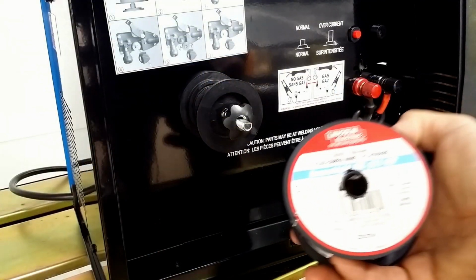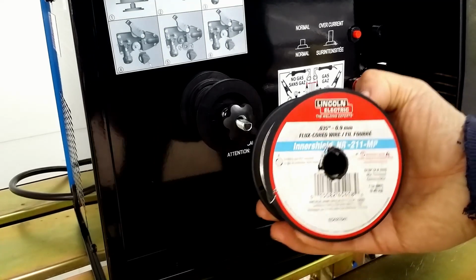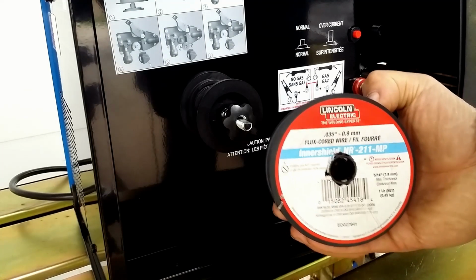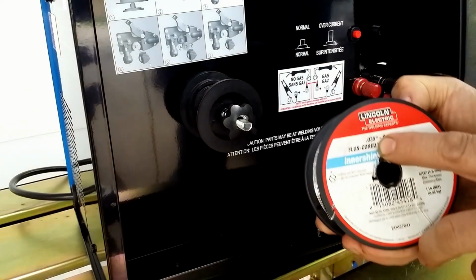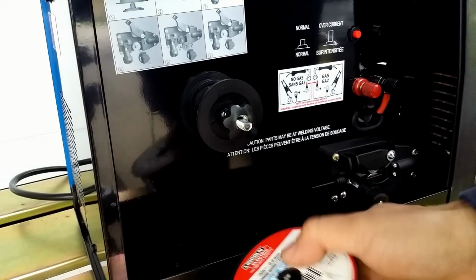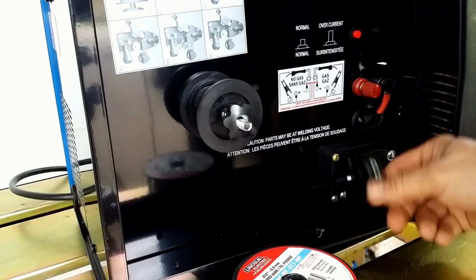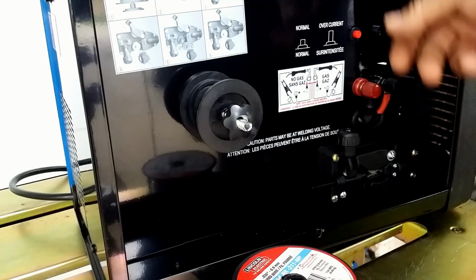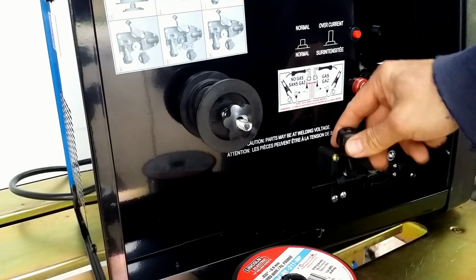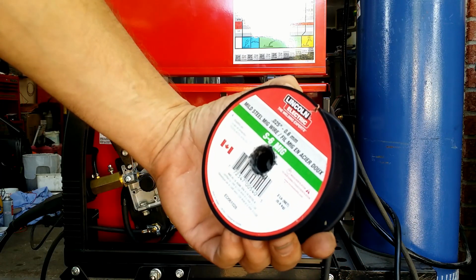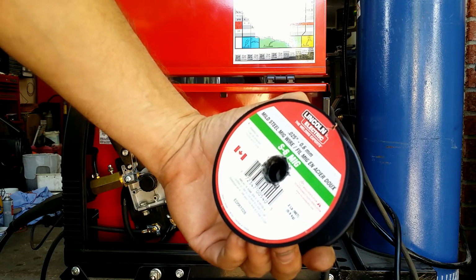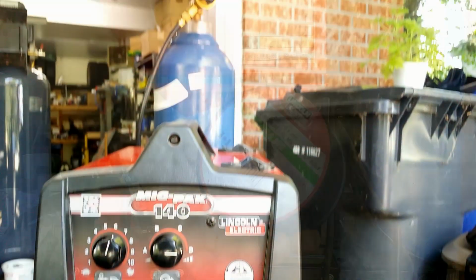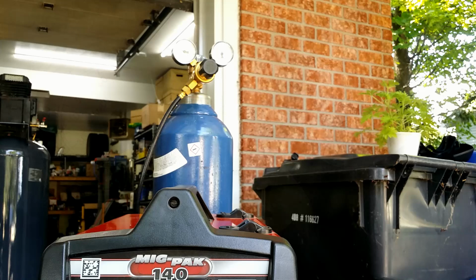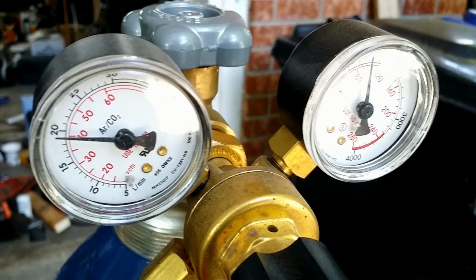But it is not enough to just melt the metal. To create a solid fusion, we must protect the molten metal puddle. Therefore, we can use welding wire with a flux core, and when the flux melts, it protects the puddle from the atmospheric elements. We can also weld with a shielding gas. And here we have two different processes that are usually called MIG welding.